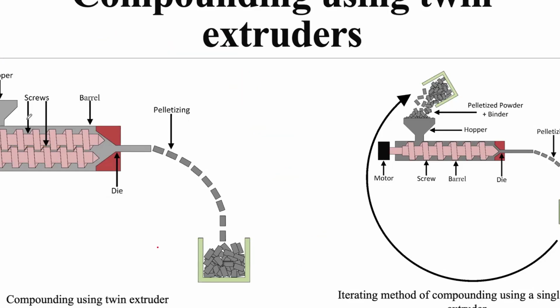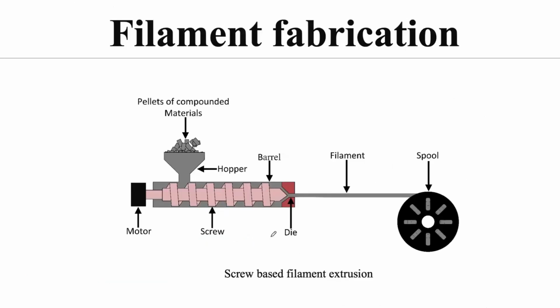And the strategy that we use for this is that once we put everything into a hopper and make a filament, you pelletize it. You cut that filament and collect those pellets, and then you feed it back into the hopper. You repeat these steps at least 6 to 7 times till the uniform proportion is obtained. So this is an iterative method that I have explained over here, and in that manner, a filament is formed.